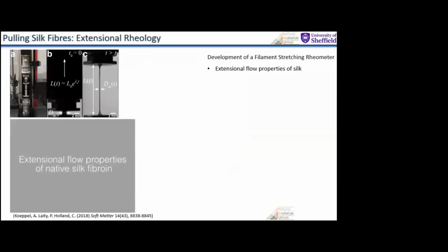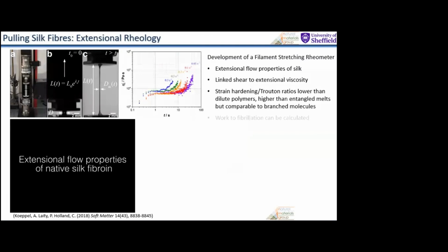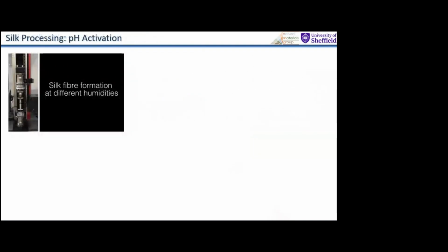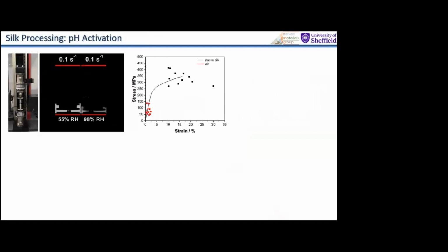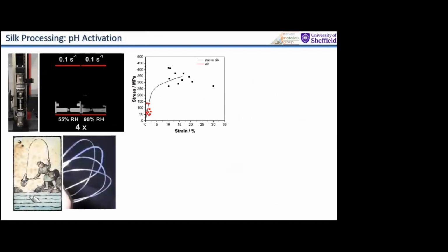We've done some more recent work by pulling silk fibers and understanding their mechanical properties. We've looked at changing humidity as we draw silk fibers from the goo into the solid fiber. We find it can be done, provided it's not too wet. You can actually draw fibers just through extensional rheology. The fibers themselves are rubbish.